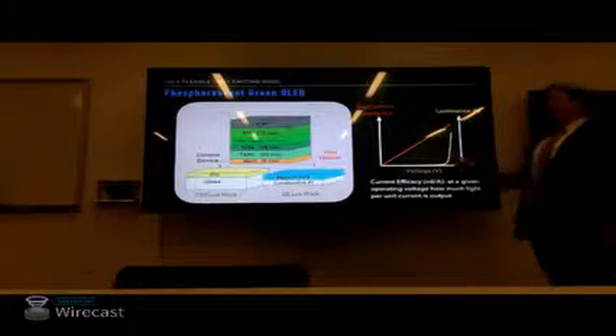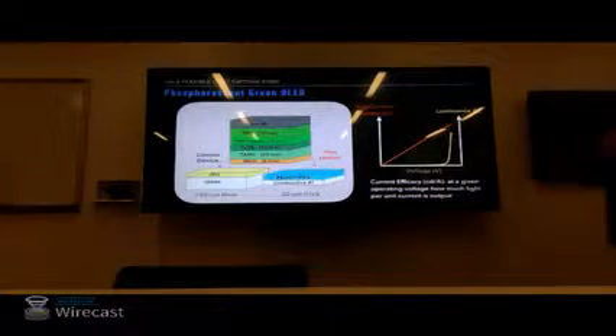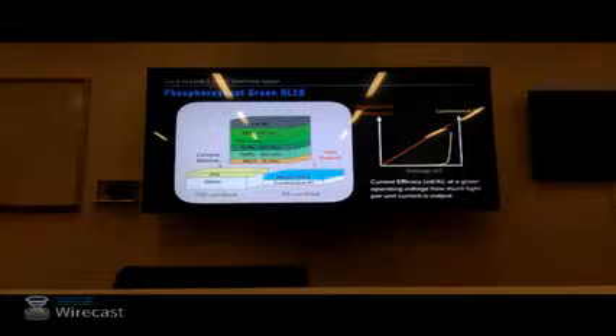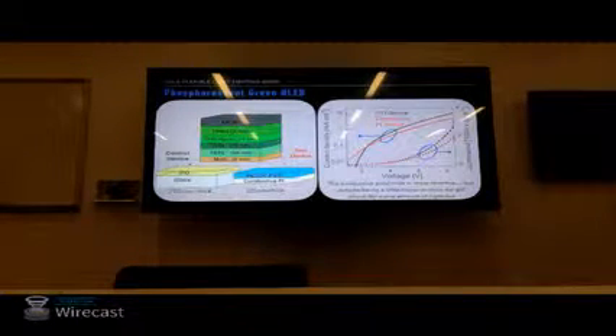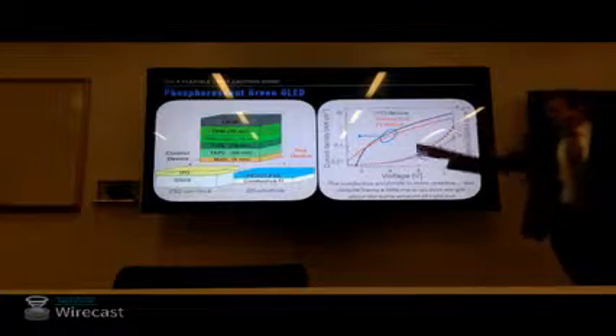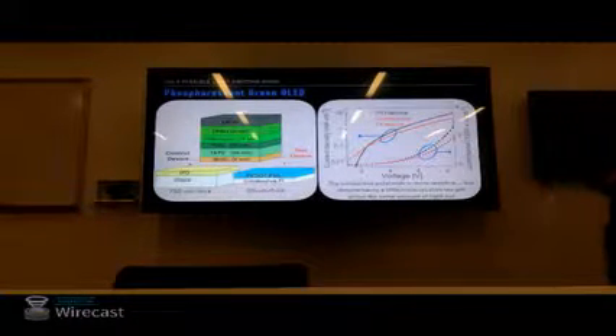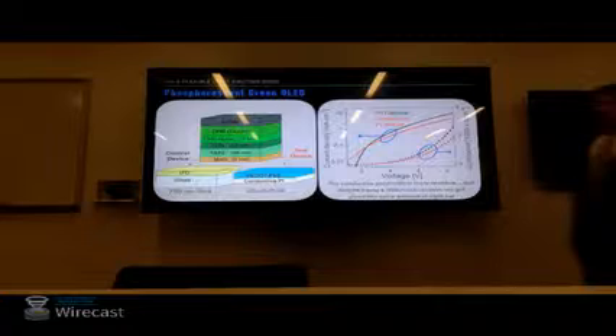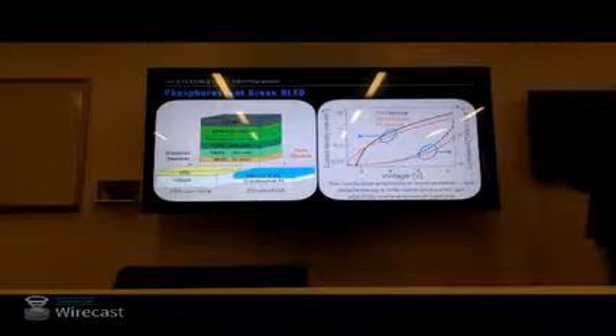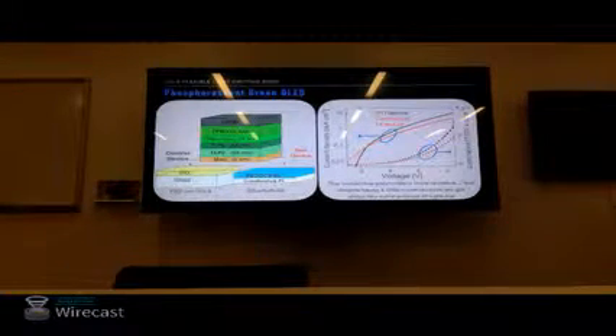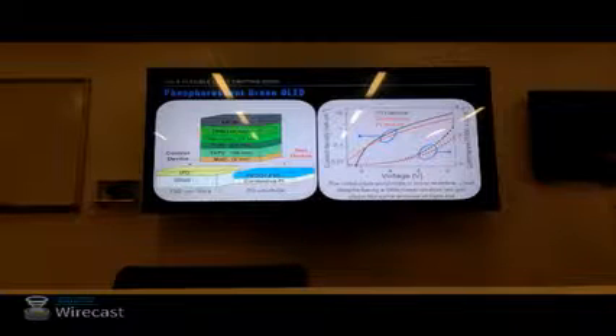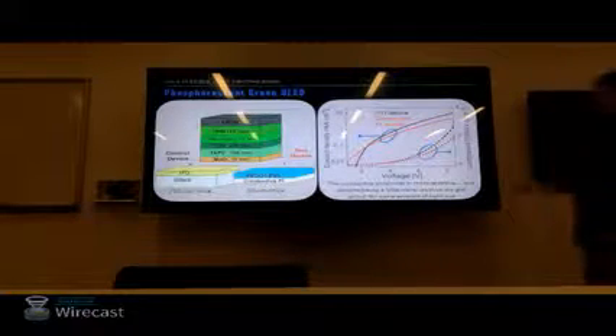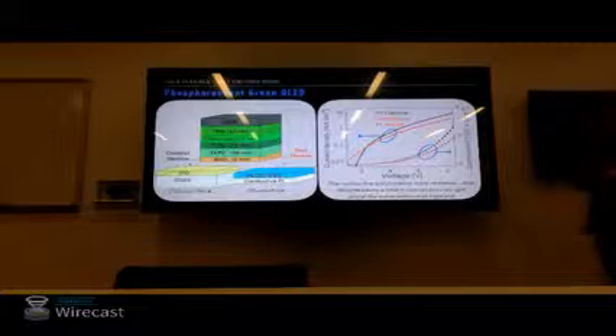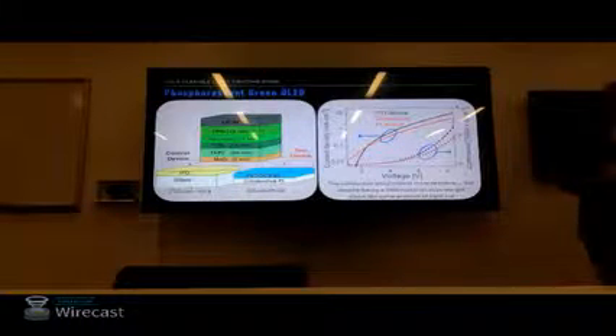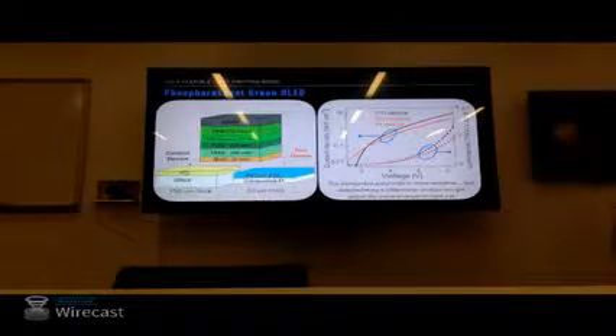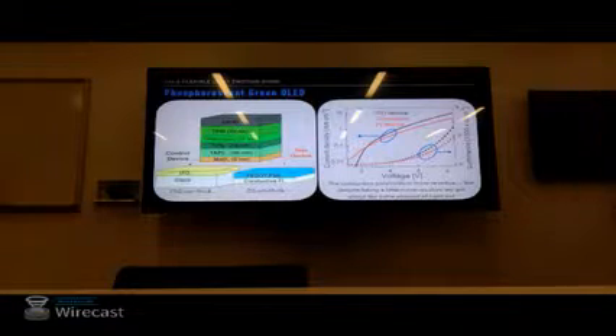And then luminance, which is measuring the light out with a calibrated silicon photodiode. So this is what we see when we compare our control device with the ITO to our test structure. What we see from the JV characteristics is that the silver nanowires are more resistive. At a given voltage, you get less current through. However, the luminance, which is not a log plot, it's linear, is not that much depressed. So while it's more resistive, this doesn't really show us whether we made a better or worse device.